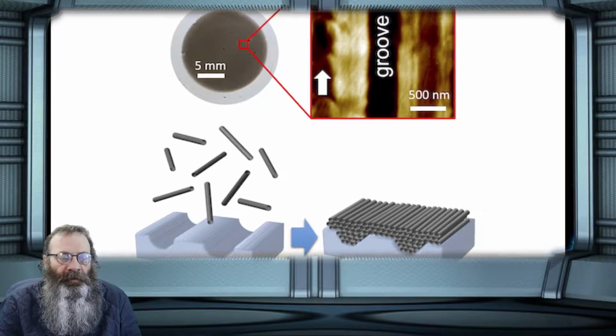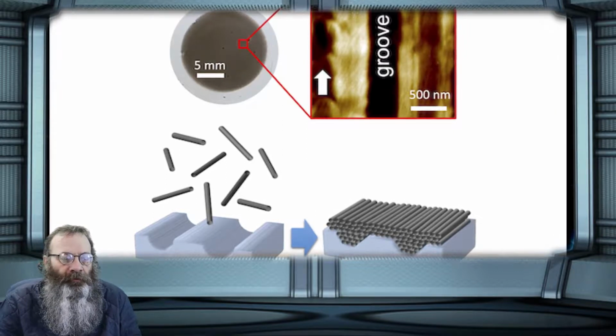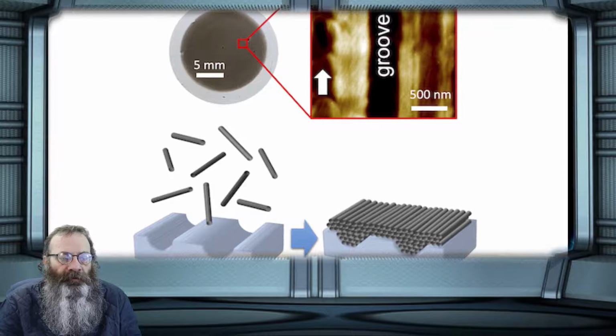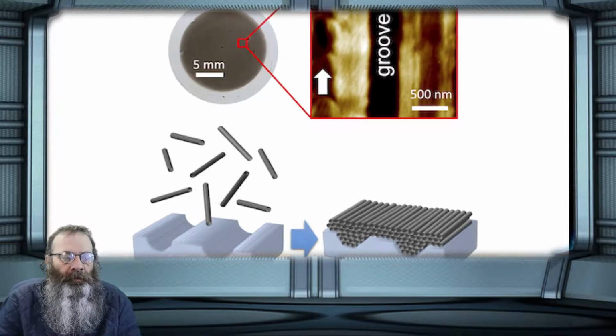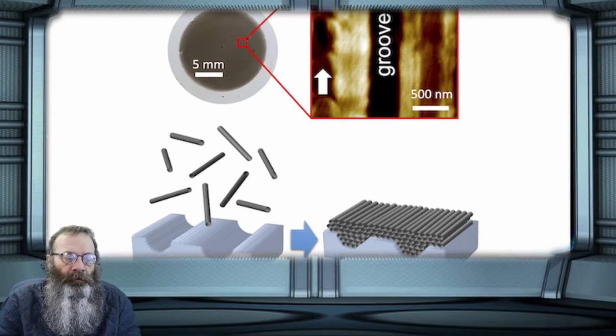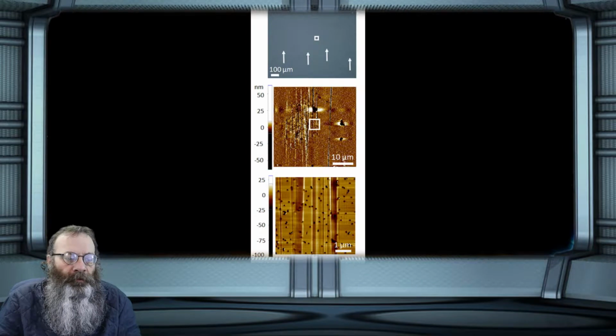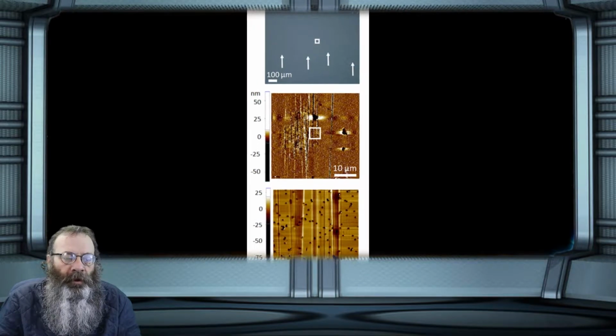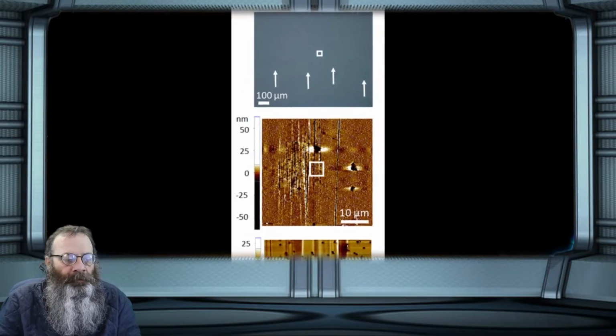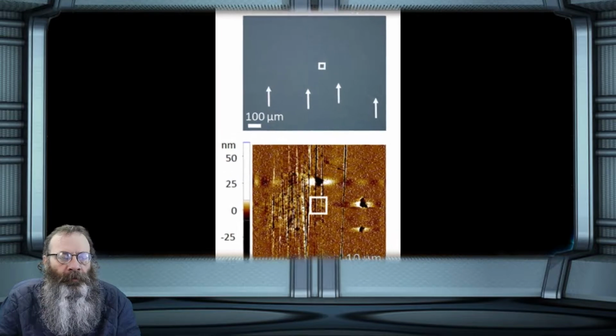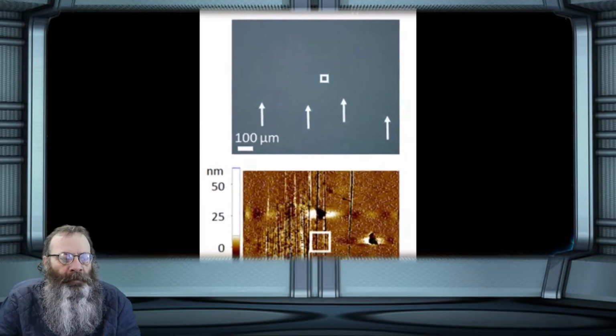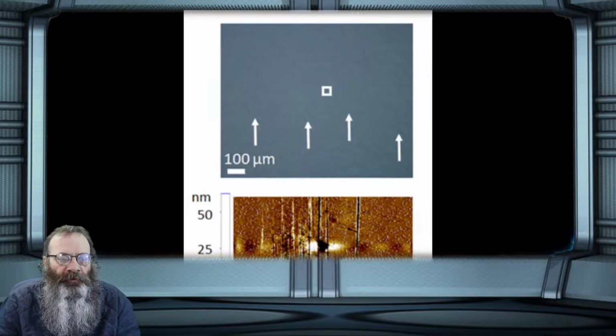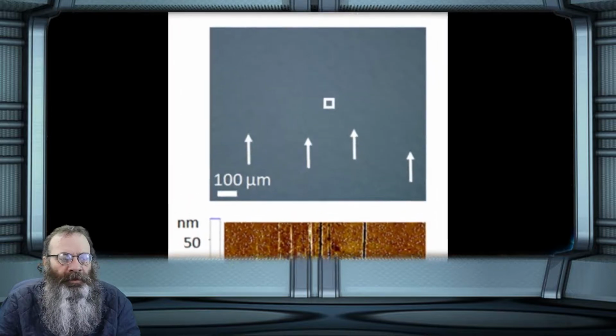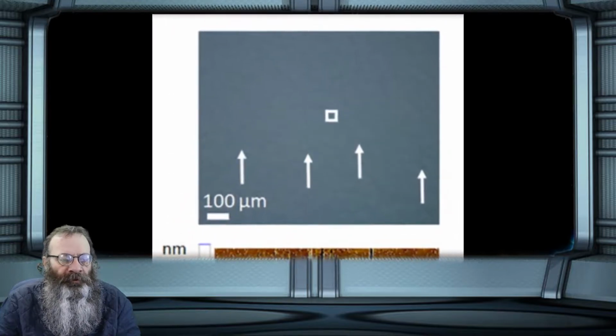Kono said his team has made highly aligned 2D crystals from solutions with a diverse mixture of nanotubes. But when we go to a single chirality solution, we were never satisfied with the alignment, he said. Now with this knowledge of grooves, we are confident we can improve the degree of alignment in the case of single chirality carbon nanotube films. Single chirality films could open the door to applications with mind-boggling potential. For example, sheets of pure carbon that convert heat into light with almost perfect efficiency.